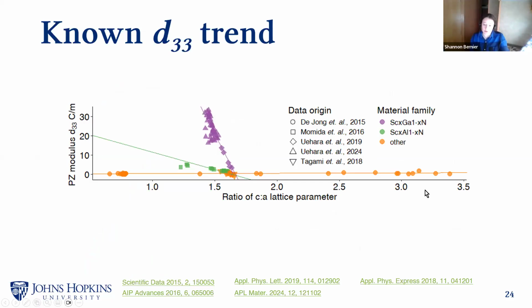So there are 3 different families here, all in the Wurtzite crystal structure, the hexagonal crystal structure. And you can see that the scandium gallium nitride family right here in purple has a different maximum value of piezoelectric modulus than the scandium aluminum nitride family. But in both cases, a decreasing C to A lattice parameter, meaning that the long axis here is becoming shorter, indicates a higher value of the piezoelectric modulus. So in these families, they've been studied a lot, and over time, people have been finding ways to reduce that C to A lattice parameter in various different ways, including thin film strain, basically, in order to try to reach higher piezoelectric modulus values.